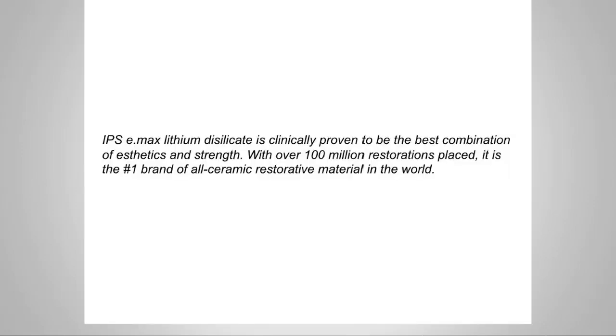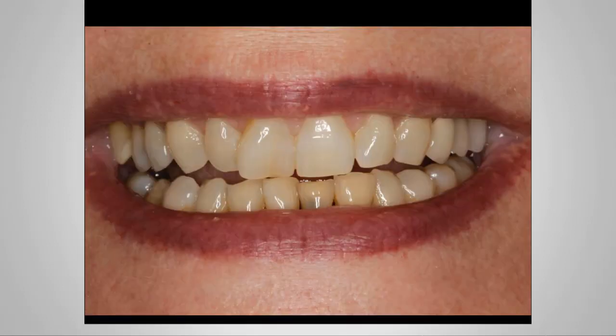Let's talk about aesthetics. So for me, Emax lithium disilicate, clinically proven to be the best combination of aesthetics and strength. Over 100 million restorations placed, and I do feel like I have to find a reason not to use Emax on a lot of my restorations. With the new multi zirconia and the MT zirconia that we're seeing now from Ivoclar, it does allow me to use that in higher stress areas in the back. And the case that I'm getting ready to show you will show you maybe where we can even mix the materials. So for me, I have to find a reason not to use lithium disilicate.